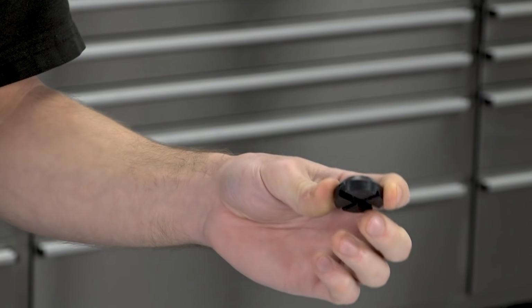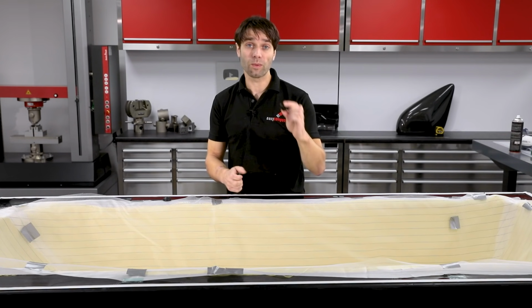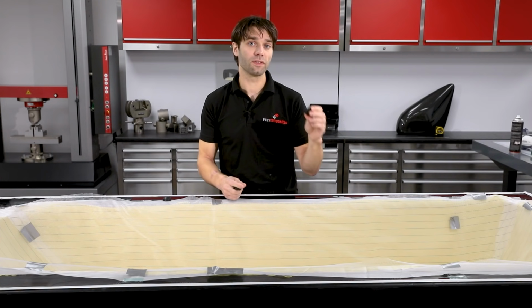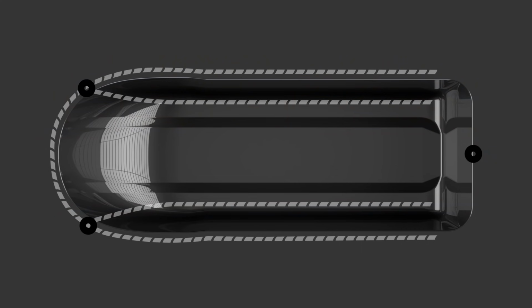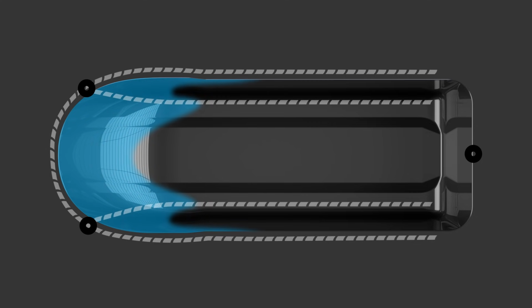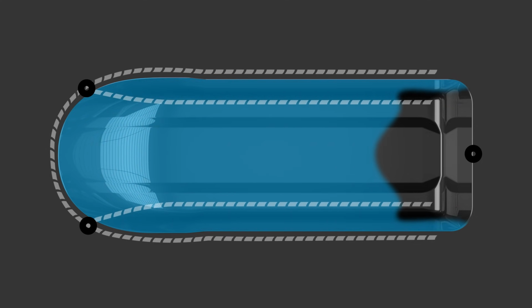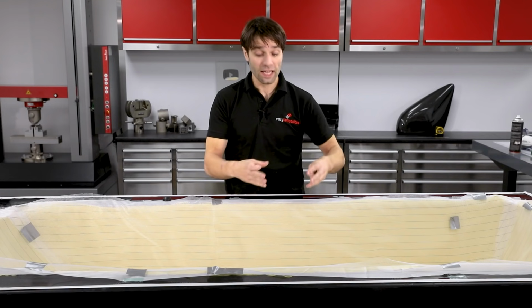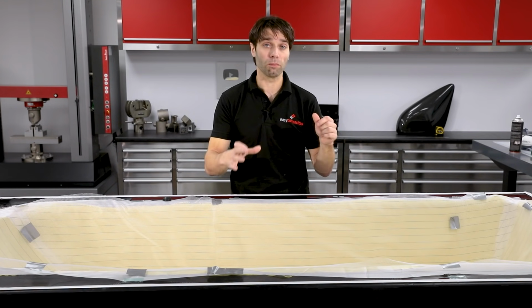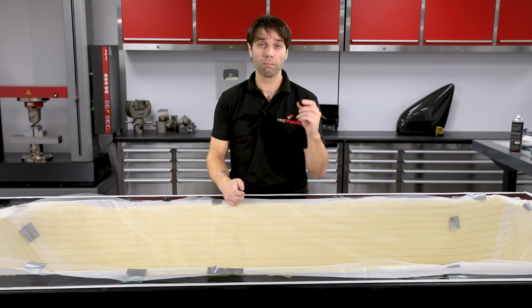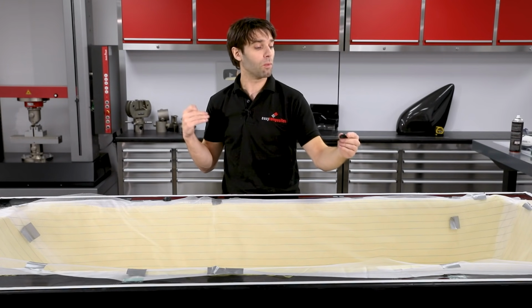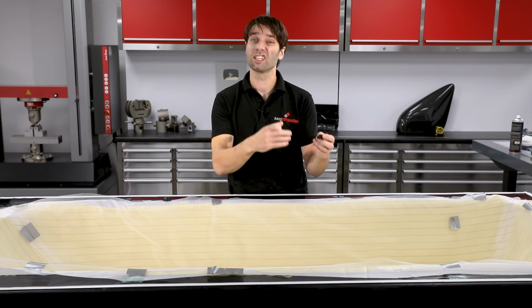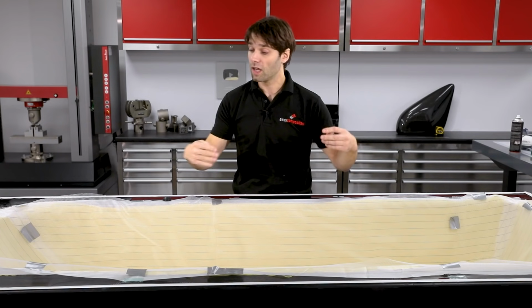When it comes to positioning the vacuum ports, the way to decide where they go is the point which is furthest away from both any resin inlets and the spirals. And that way it will converge at that point last, or at least that's the theory. If you've got a complicated shape and you can't perfectly work out where that's going to be, put more in. It's no problem to wait for the resin to hit one of these. As soon as it does, you can clamp that one off and you can have another one.